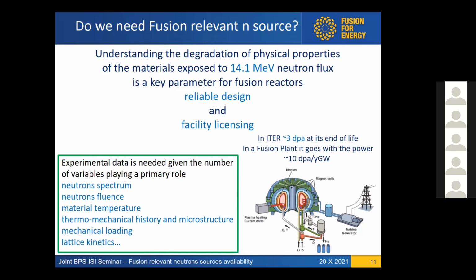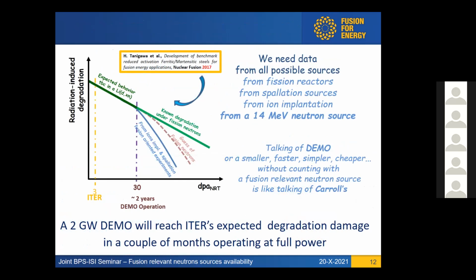Certainly, a power plant will very likely try to be comparable to that of a fission reactor, so it should be 3 gigawatt thermal power. So it would be far above, 10 times more than what ITER will suffer at the end of its life. And this is the situation we have now. I mean, we know very nicely because in fission reactors, we have been able to have experimental fission reactors from the very beginning. So there was no problem to test materials in real conditions. In fusion, we cannot do that. We don't have a fusion reactor. ITER will be the first fusion reactor to work in steady conditions.